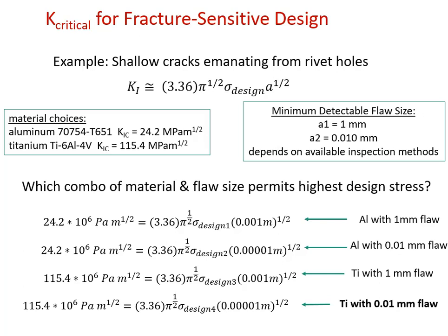Let's assume we have a couple of material choices. We have aluminum 7075-T651, and it has a K1 critical, which means its fracture toughness in mode 1 loading under plane strain conditions, the critical stress intensity factor K for that material, is 24.2 megapascals meters to the 1/2. K1Cs are called out in stress times length units to the 1/2, and that's because of that A to the 1/2. Our second material choice is much higher, 115.4 megapascals meters to the 1/2, and that's titanium in this case. It could have been any material; they'll all have their own material-specific K1C.